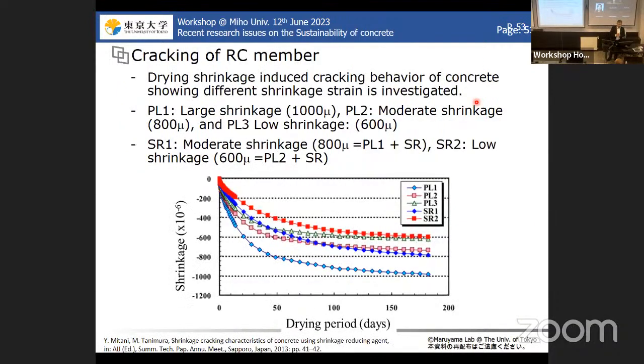Then again, we tried to put the SRA in concrete. And as I introduced, we defined the shrinkage of concrete with similar materials prepared. And when we add the SRA to this concrete, we see the shrinkage of this concrete. So these two shrinkages are comparable, SR1 to PL2 and SR2 to PL3.